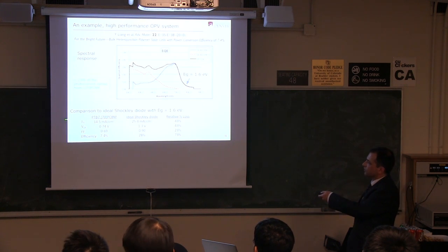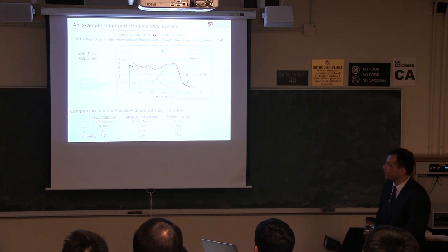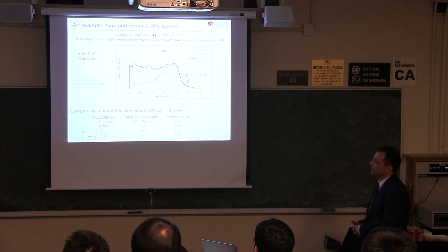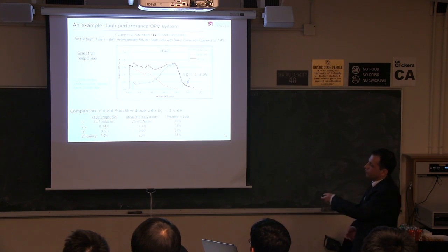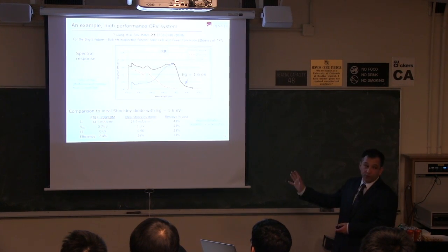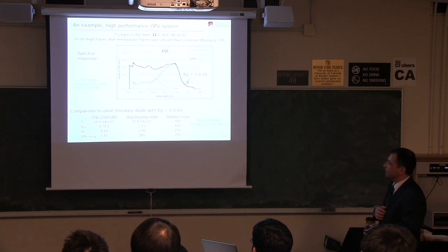So here we have about 15 milliamps per centimeter squared short circuit current, ideal diode about 25. So we've lost 43% over the ideal in terms of current. Voltage, we're at 0.7, ideal is 1.3, have lost another 43%. And fill factor, we're at 0.7 roughly, ideal is 0.9, lost 23%. So overall, we're losing, in this case, 73% relative to the ideal diode. Obviously, a long way to go.